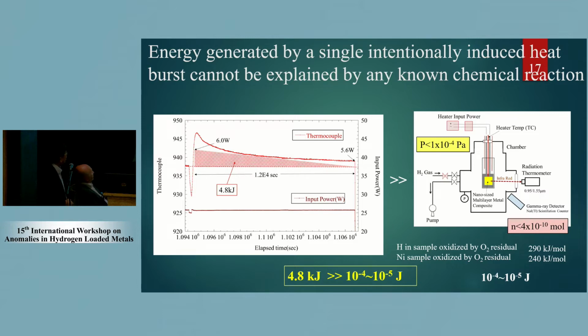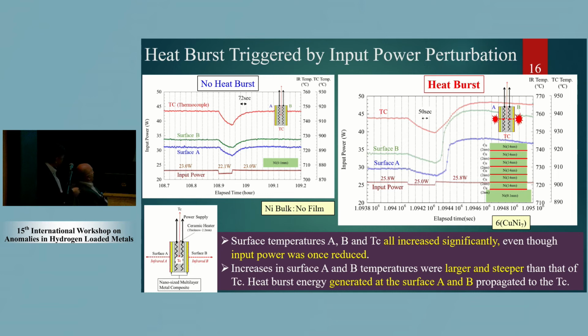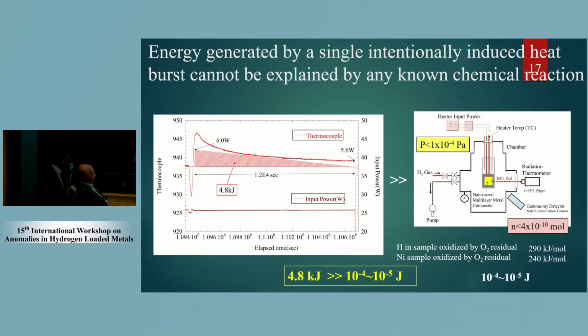And we estimate the energy generated by a single intentionally induced heat burst, and it cannot be explained by any known chemical reactions. Okay. In this case, this is the intentional heat burst region. It corresponds to here, and we extend the time span. This is the thermocouple temperature. The thermocouple temperature significantly increases and gradually decreases. This point corresponds to 6 watt, and this one corresponds to 5.6 watt. So the energy released by a single intentionally induced heat burst is at least larger than this region. So 4.8 kilojoule is obtained.